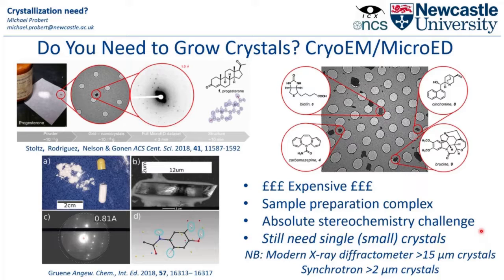Determining the absolute stereochemistry is a challenge. It's a challenge that's mostly solved now using analysis of dynamical scattering, but it is definitely more of a challenge than it is from single crystal X-ray data. And of course you still need single crystals. They are just much smaller than for X-ray diffraction analysis. I've put some scales on here for the size of crystals required for various places. For cryo-EM and micro-ED, you can scale this down significantly.